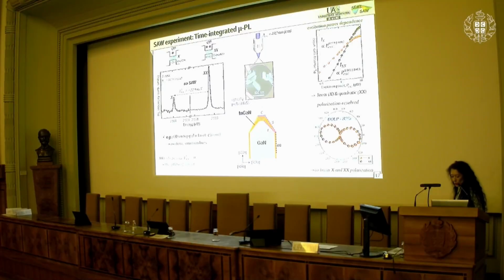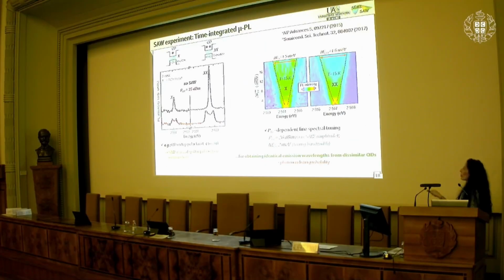So now when we apply the acoustic wave, this spectrum undergoes an apparent splitting of the two lines, as you can see here, and this splitting increases continuously as we increase the acoustic power, or the RF power that we apply to the IDT. So these experiments show that we can efficiently use surface acoustic waves to fine-tune the quantum dot emission energy within a bandwidth of around 2 milli-electron volts.